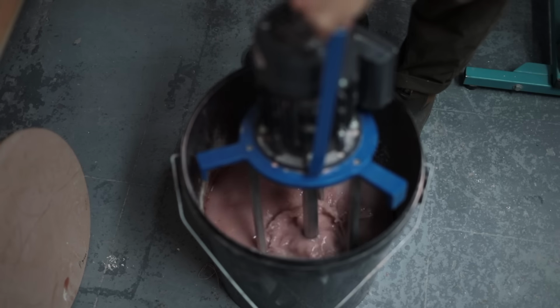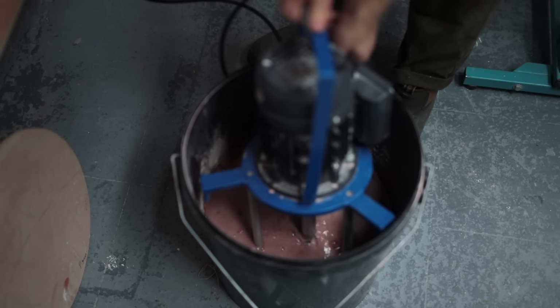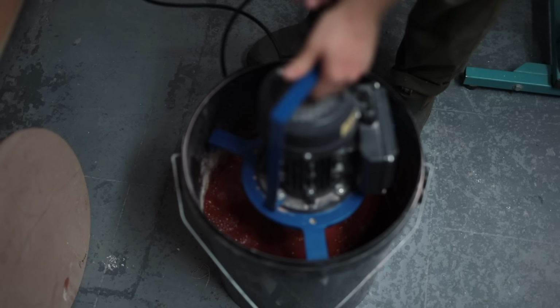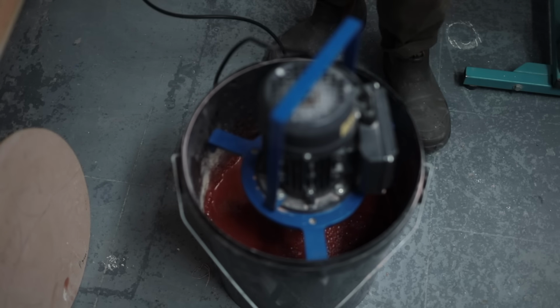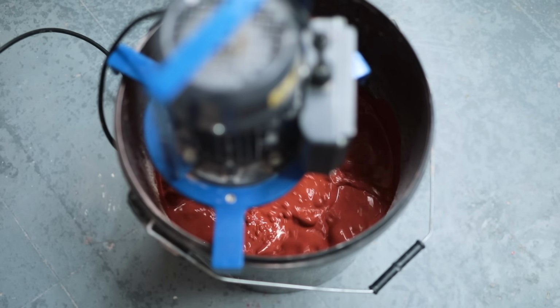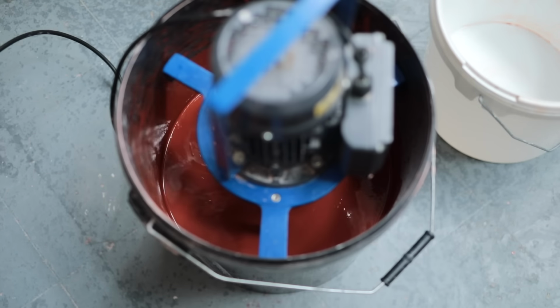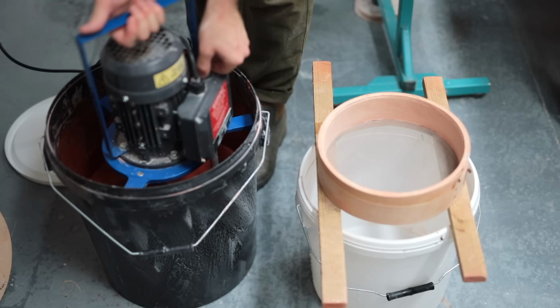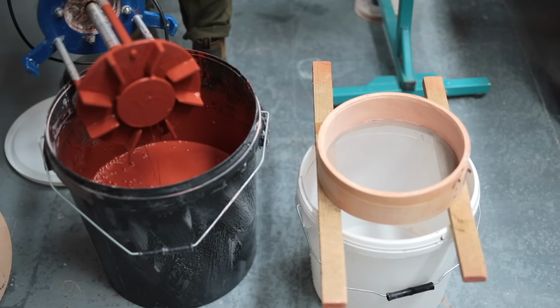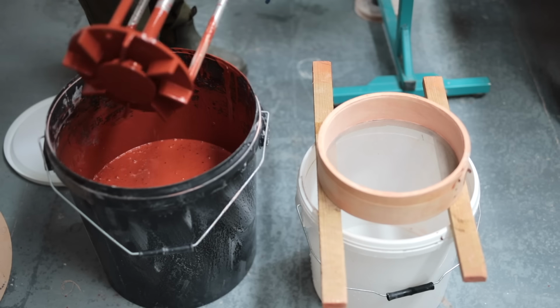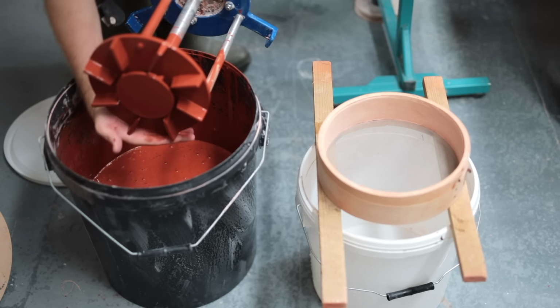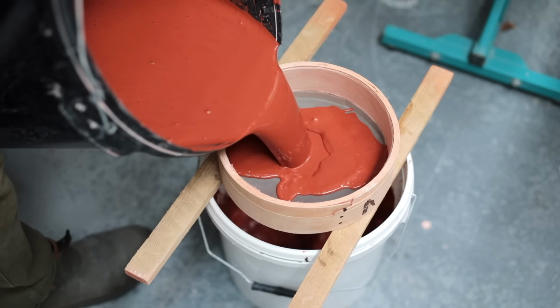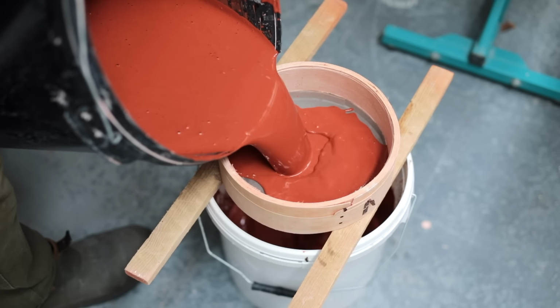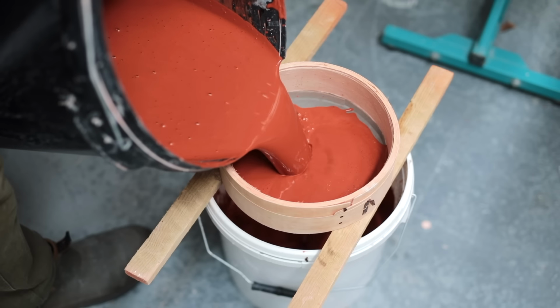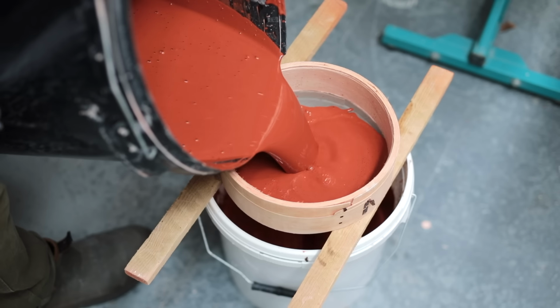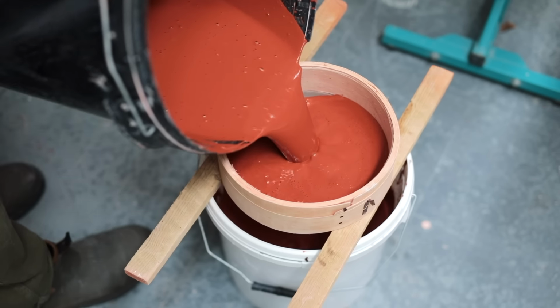All of this is then thoroughly combined with a glaze mixer, and I like these wide buckets as the entire mixer can fit inside, slotting in right to the bottom. About 10 minutes later, I switch it off and tap off most of the excess glaze. The glaze itself was then passed through a 100 mesh sieve, and this step is crucial as it fully combines everything, as without this there may be some larger particles that don't fully melt in the final glaze, resulting in specks and irregularities appearing in it.